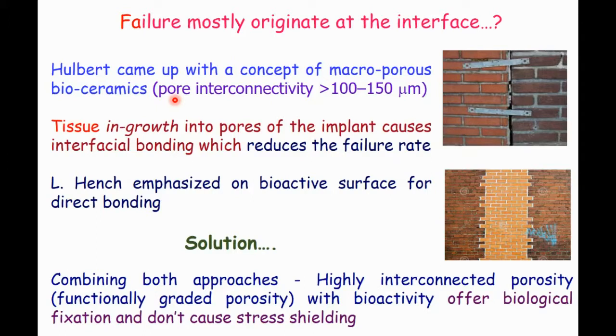But Larry Hench, another scientist from the University of Florida, proposed that if we use bioactive materials, then the material can be bound to the tissues, and therefore tissue and material will have very strong bonding. Both these theories were proposed in the 1960s, and if you look at the last decade, all the implants came off a combination of these two approaches. Hulbert says it has to be a highly interconnected porous structure, and Hench said it has to be bioactive.